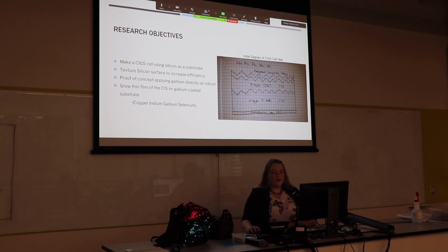Then on top of it, we would grow our copper indium gallium diselenide film. Instead of growing all of that together, we applied the gallium directly to the silicon and then grew the film on top of the gallium. And then during the annealing step, the gallium would hopefully diffuse into the rest of the film and create our full CIGS cell.